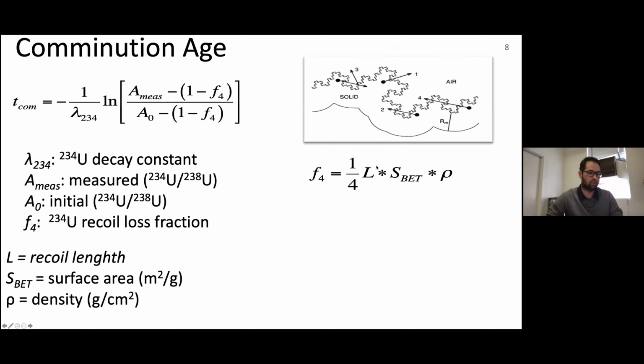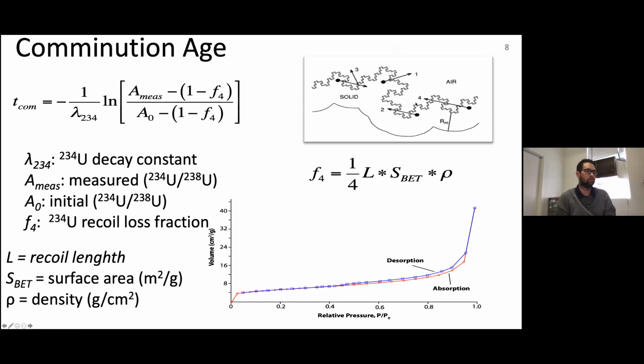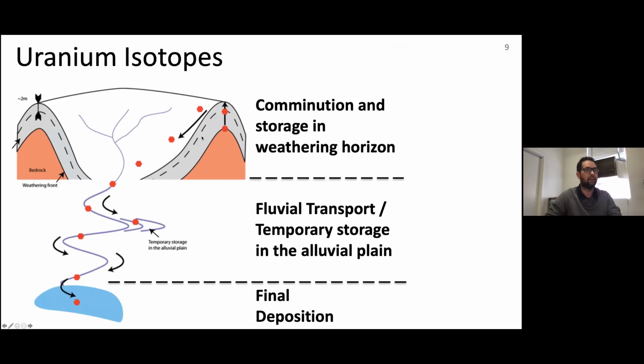And this recoil loss factor in the end depends on the surface area. So the bigger the surface area of our grains are, the more surface we actually have to lose our uranium-234 into the surrounding pore space. So we can measure the surface area by means of gas adsorption analysis, and we get a number in square meter per gram. And we need to know the recoil length, because the distance that the nuclide is displaced, the density, and then we can feed that all into our equation to calculate what was termed in the early publications Comminution Age. I will clarify that a bit more now, what this terminology is used for.